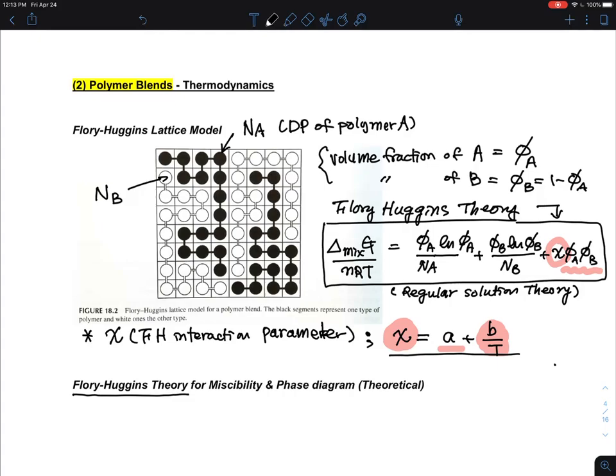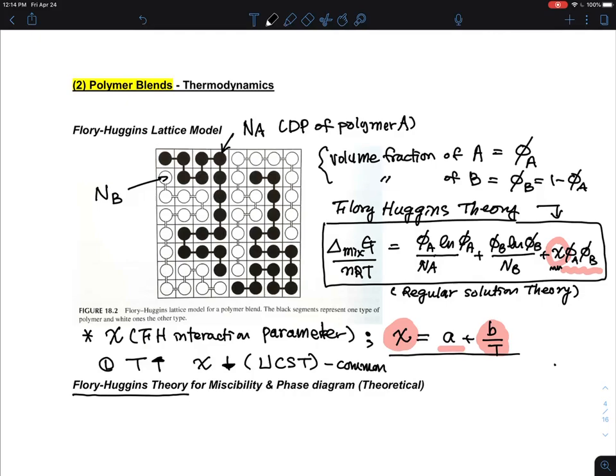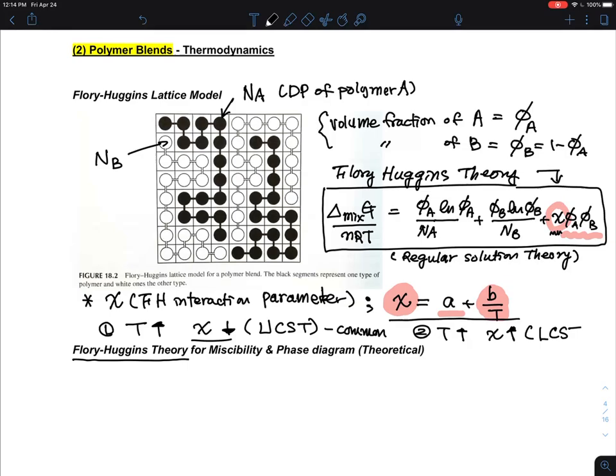The beauty of Flory-Huggins theory is the simplicity of this Gibbs free energy representation, but there is a price to pay — realistic deviations from the idealized model require more complicated interpretations of chi. In simple terms, when temperature goes up, chi comes down; this is the case for UCST, which is quite common. Sometimes chi goes up with temperature, and this is called LCST, which has also been observed in polymer blends.